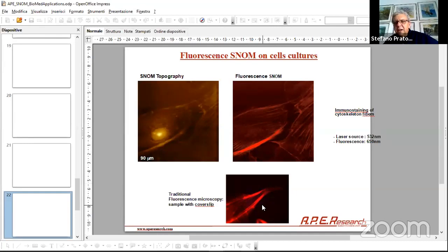They look similar, but in reality, they are completely different. Because with the SNOM, we can see the bright part here again, but with the SNOM, we can also see this very shallow part here. See this part here? We can see some fluorescence contrast. And with the confocal microscope, you don't see anything, because you are not in the same range of focus. You remember with the confocal, you have a depth of focus between 100 to 200 nanometers.